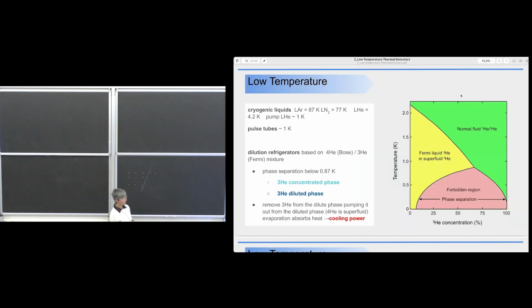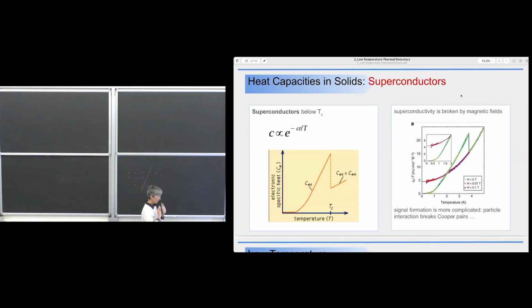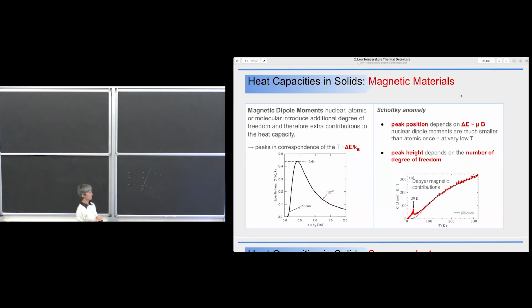So basically the real choice is to use a material that is a dielectric or a semiconductor, because when you go to very low temperature, a semiconductor behaves as a dielectric material. A semiconductor is a material where the gap between the valence and the conducting band is of the order of the thermal energy. But when the thermal energy goes very, very low, because you are at low temperature, a semiconductor behaves as a dielectric material. So the strategy is you have to use a crystal, and this crystal has to be a semiconductor and should not have magnetic properties. Okay, these are the slides with the magnetic properties. Because if you have a material that has, yeah.